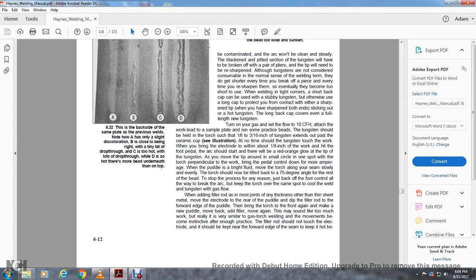Turn your gas flow back to 10 cubic feet an hour. Attach the work lead to the sample plate and run a simple practice bead. The tungsten should be held in the torch so that 1/8 to 3/16 of an inch of the tungsten stands out past the ceramic cup. At no time should the tungsten touch the work.